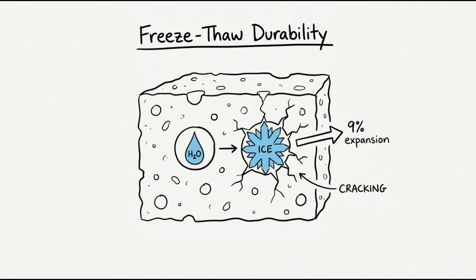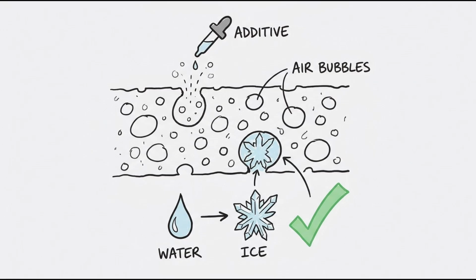Third, durability against freeze-thaw cycling. Concrete is porous at a microscopic level, and water sitting in those pores will freeze in winter, expand by about 9%, and physically pry the material apart from the inside. Cycle after cycle, year after year, until the surface starts flaking away. The clever fix for freeze-thaw damage is almost invisible. Air-entraining admixtures deliberately whip millions of microscopic air bubbles into the wet concrete. When trapped water inside the material freezes and expands, it has somewhere to go, into those tiny air pockets, instead of cracking the surrounding concrete apart.